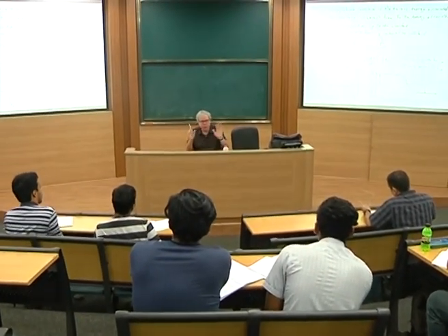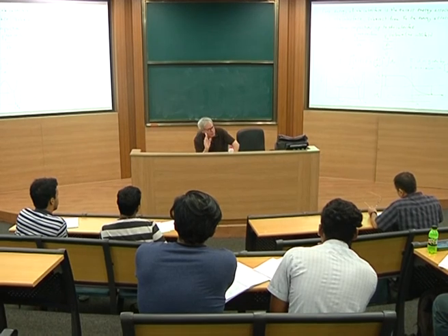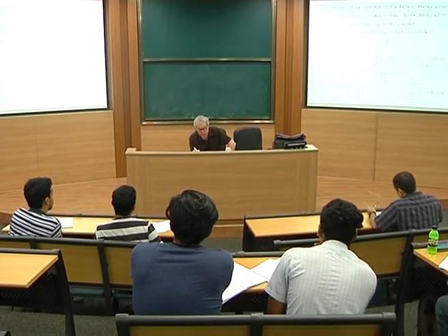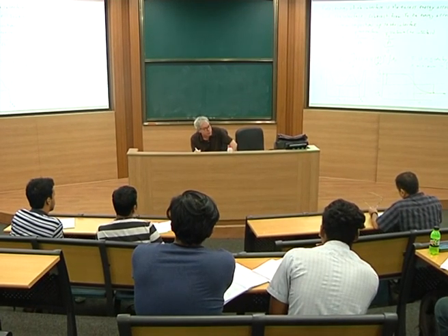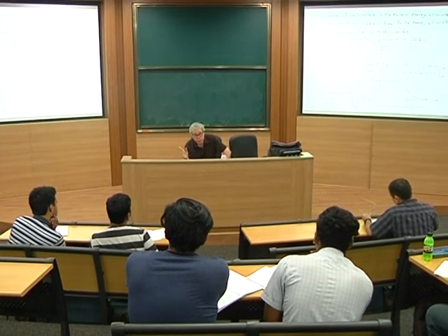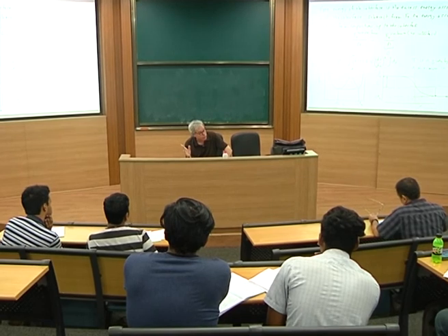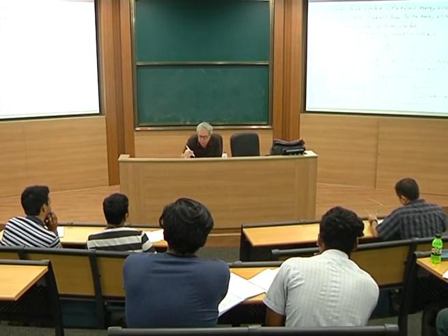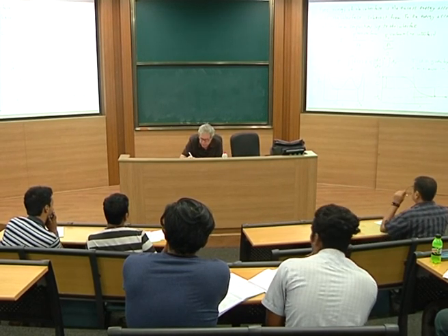Okay. Speaking a little quickly. These are good questions. I want to make sure everyone understands. It works for any free energy function that's continuous from one phase to another, right? It has to look like this. So it can be a Ginzburg-Landau. It can be regular solution. It will work. The problem becomes, and we were talking a little bit about this yesterday with some of you,